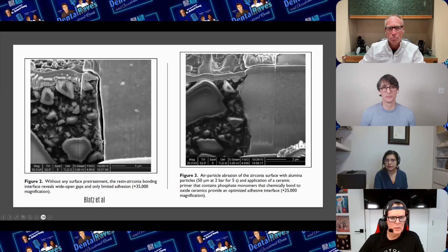As you can see, this limited scanning electron microscopic imaging, I must say, investigates without any surface pretreatment. The resin zirconia bonding interface reveals wide open gaps and only limited adhesion. I think you can see my cursor over here. So that's the gap that you see. And then in the second image on the right, you can see that air particle abrasion of the zirconia surface with alumina particles at 50 microns, 2-bar pressure, and application of a 10-MDP containing ceramic primer actually gives you an adequate chemical bond, an optimized adhesive surface as reported by this paper.